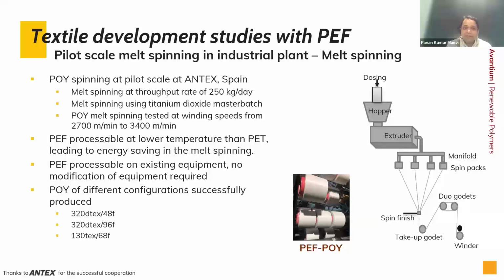And we made different kinds of yarns with different numbers of filaments and counts. This yarn was actually the POY, without any high level of drawing. All yarn and process development took place in the existing PET equipment. So it is very well proven that we do not need any optimization in the instruments or the machines. And PEF was processed at a lower temperature than PET. That means there is a huge potential of energy saving in the melt spinning process.